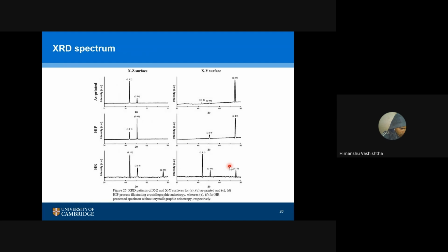Now we have captured the XRD spectrums, which give us a pretty good idea. Let's focus on this first row - that's the XZ surface, that's XY. For the XZ surface, you're seeing the orientation is preferred in 111 and 200 directions. In the XY surface, it's preferred in the 220 direction. So that's a clear-cut case of microstructural heterogeneity, right?